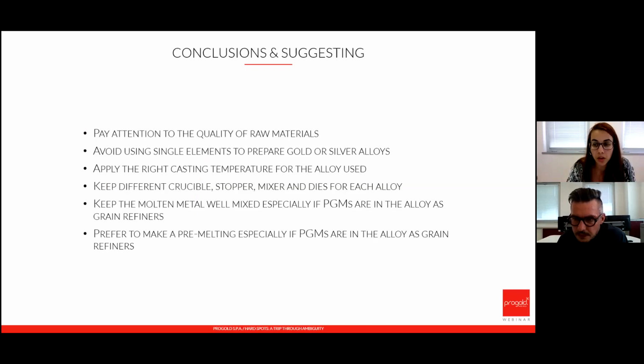Okay, so this refers to the case in which we modify the alloy, as I explained in the case of this person adding cobalt just to harden the pieces. So avoid it, because if you don't know what's inside or the quantities of what is inside, you might get reactions you do not want. And it also refers to being careful when you mix your own alloys. If you put gold and silver together, you're not going to get more problems. But if you start to get creative and add all the elements on the periodic table, things might happen.